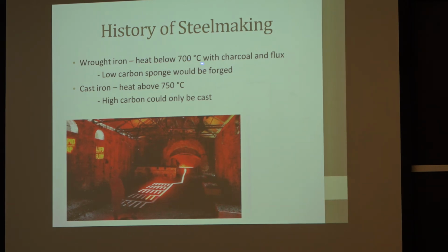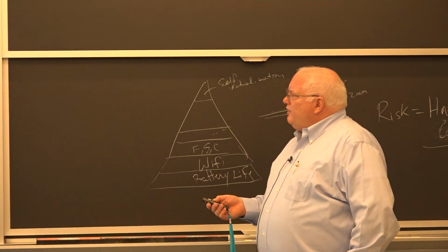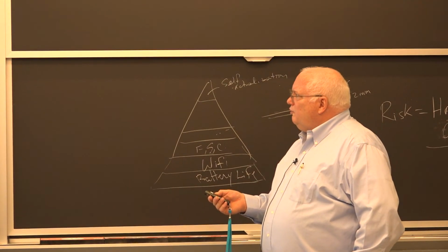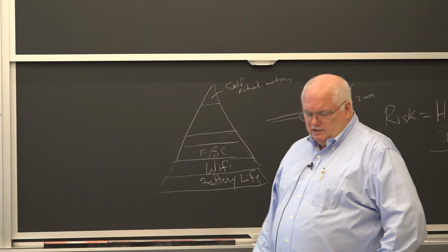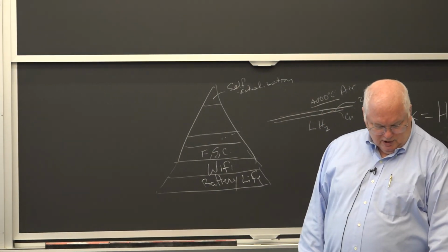They later learned to basically not do this at 700C, but to take the cast iron and blow oxygen through it and make puddled iron, okay? That's at higher temperatures. And that's what they were doing in the 1850s when Bessemer came along. He was trying to improve puddling of iron, and he learned a way to make steel without puddling it, okay? But this is low carbon. It would be forged, and high carbon has to be cast and is brittle and cannot be forged. It will break when you hit it.